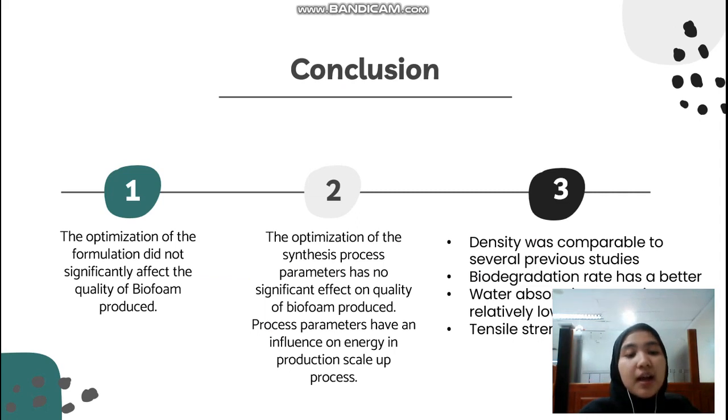The conclusion. The optimization of the formulation didn't significantly affect the quality of the Biofoam produced. The optimization of the synthesis process parameters has no significant effect on the quality of the Biofoam produced, but can influence energy and the production scale-up process. Density was comparable to several previous studies. The biodegradation rate is better, but water absorption capacity was relatively low, and so was the tensile strength.